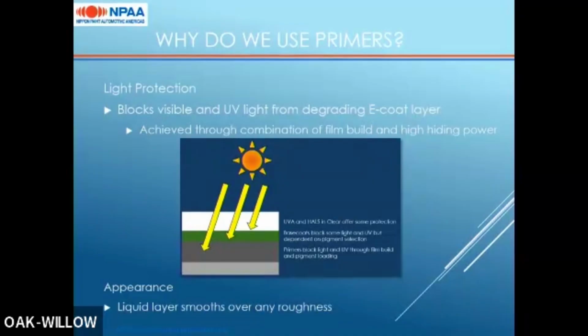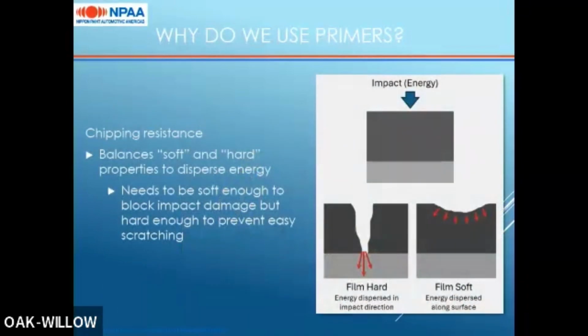Primers also help improve appearance. They cover up any defects in the E-coat layer and anything that needed to be repaired before top coat is applied. Additionally, primers help with chipping resistance. They balance soft and hard properties to disperse energy. So in general, they need to be soft enough to prevent impact damage, but hard enough to prevent easy scratching.